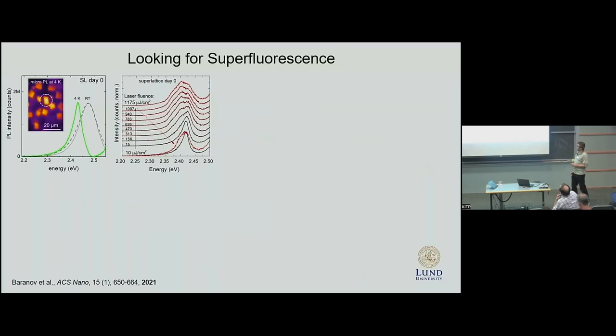In the first case, in collaboration with a group in Lecce, we looked at freshly made superlattices of perovskite nanocubes. When we cooled them down, we didn't see the appearance of any additional features, and when we tried to check whether we saw anything with increasing laser fluence, we basically just photo-damaged our superlattices.